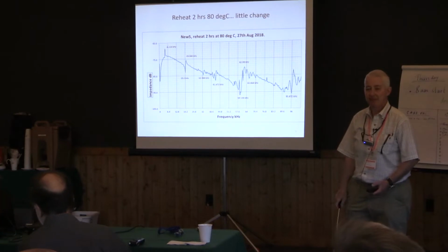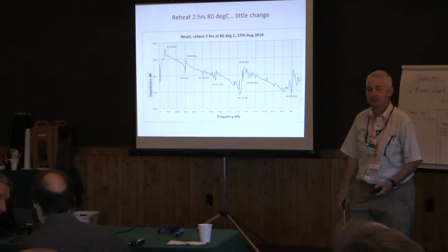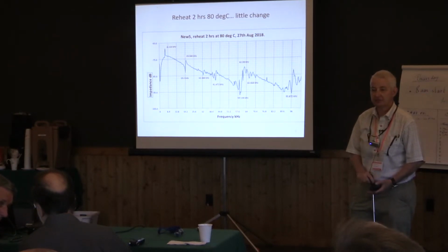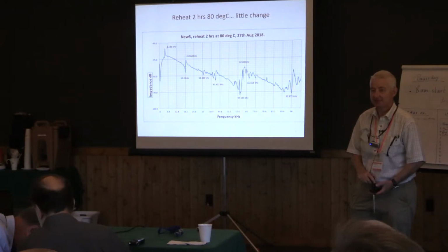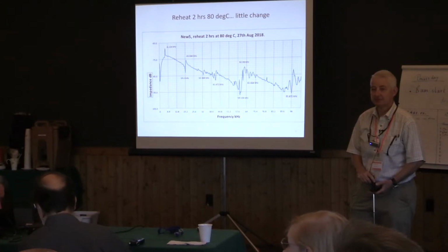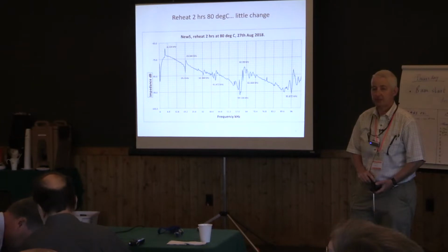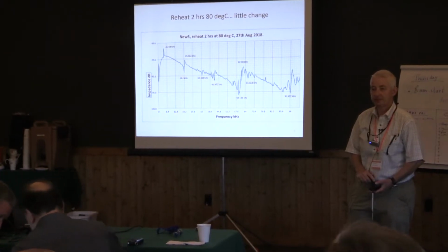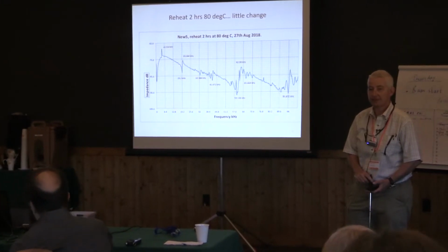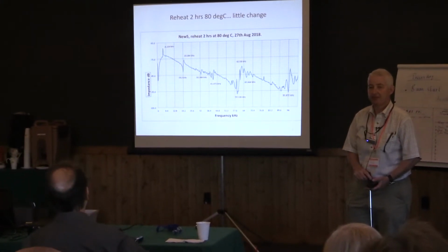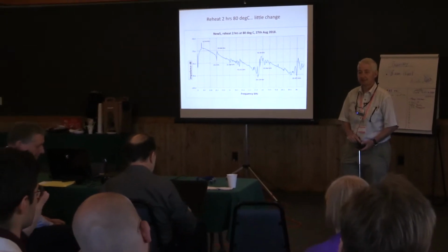If you're emphasizing the propagation resonance as 36 kilohertz, that is present in your system, then I would suggest measuring the current and the voltage with the amplifier and the separate transformer connected to the thruster, and then do a frequency sweep. You can get the impedance curve from your voltage and current measurements. Then you would be able to show maybe a significant dip in the impedance at that frequency. Right. No, it's good advice, and I'll take every advice I can get.